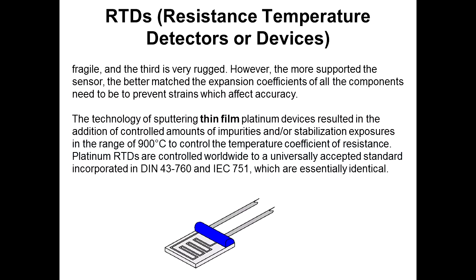The technology of sputtering thin film platinum devices resulted in the addition of controlled amounts of impurities and/or stabilization exposures. They sputter molten platinum onto usually a little ceramic chip, and then they laser cut it to trim it to get the proper resistance levels. And these are good up to about 800 to 900 C and are used throughout industry because they're much more rugged and vibration proof than wire wound RTDs. And these are built to either the DIN 43760 standard or the IEC 751, which are pretty much comparable.